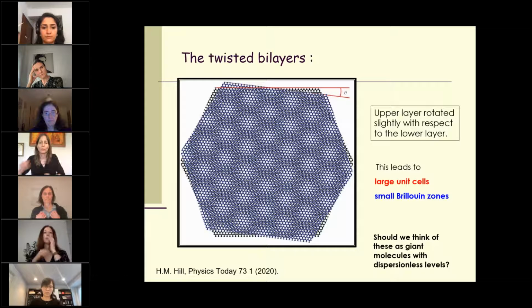You have these layers of transition metal sandwiched between the anion layers, and in any material, these sandwiches are coupled to each other by very weak van der Waals interaction. And so this has led to a very cheap epitaxy being possible, the van der Waals epitaxy, where even using a small sellotape or a Scotch-Brite, you could pull out one or more layers, and in a controlled manner, you can form heterostructures in any manner.